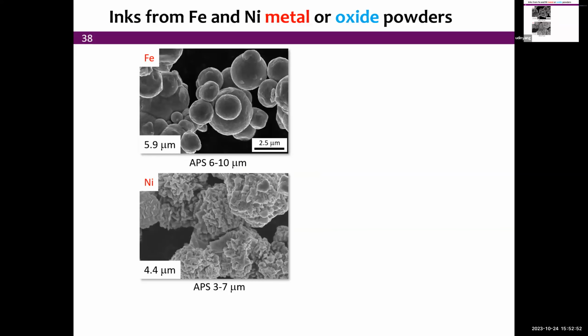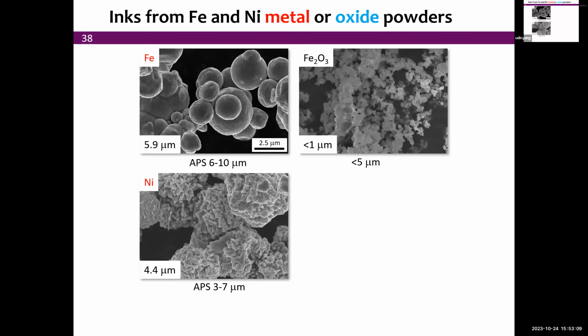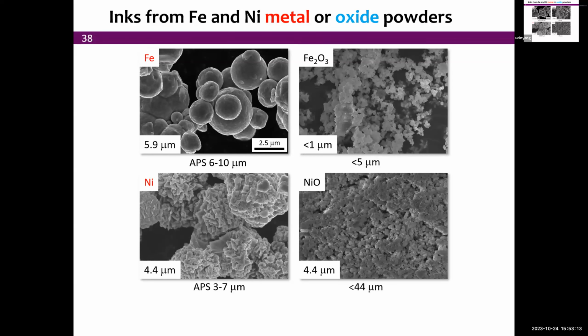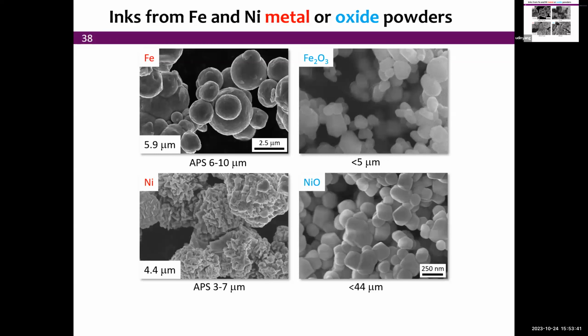And if we look in a little bit more detail, here are the iron powders. Here they're maybe about 2.5 microns in diameter. There are nickel powders, advertised at 4.4 microns, what you get on the bottle or the website. But really, you can see that they consist of much finer subparticles. Here's the iron oxide that we use, and here's the nickel oxide. Most probably those metallic powders were made by the manufacturer by reduction of much finer nickel oxide, which is precipitated from suspensions, and as a result is much finer. So it does make sense that this is going to reduce much faster and sinter much faster than those relatively large boulders, which are still 2 to 3 microns in diameter. At higher magnifications we see that this nickel oxide is really sub-micron, so really nanometric, and so is the iron oxide powder.